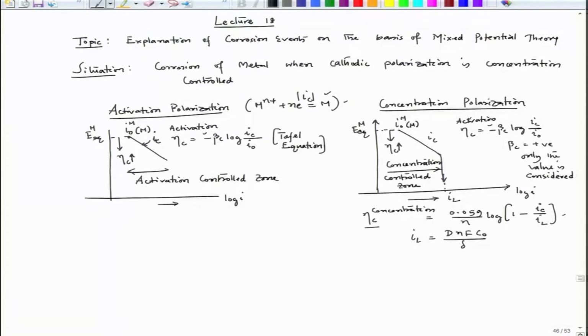So, in these two cases, the corrosion pattern of an active metal compared to that cathodic reaction can be different. That is the situation we are talking about, corrosion of metal when cathodic polarization is concentration controlled. Till now, whatever situations we have considered are all within this activation control zone, where the cathodic as well as anodic reactions follow Tafel equations, which means both are activation controlled.